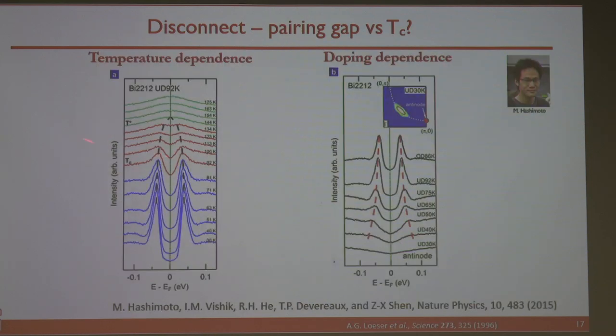The third one, of course, is the so-called pseudogap or the normal state gap. In particular, this suggests it appears above TC. Here I'm taking the spectrum at the antinode as a function of temperature. This is a symmetrized spectrum. As you increase the temperature, by the time you reach TC, the gap doesn't close. It closes at a temperature much higher than TC. If you look at this, the temperature evolution of this gap is so smooth across TC, it may as well be the same. So this says, hey, looks like there is some pairing above TC.